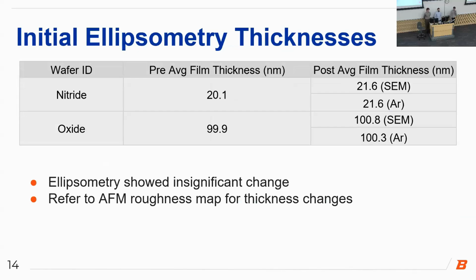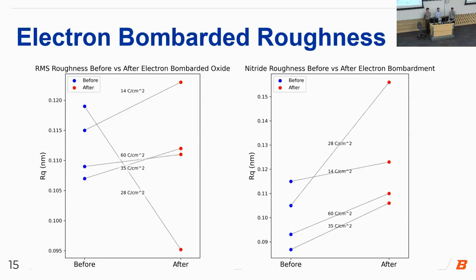As I stated previously, our pre-processing thicknesses were 20 nanometers for our nitride films and 100 nanometers for our oxides. And post-processing, these seem to have increased. We attribute this to a difference in n and k throughout the samples due to various native oxides and other contaminations on our films. In regards to the roughness of our samples pre and post treatment, they are basically atomically flat.